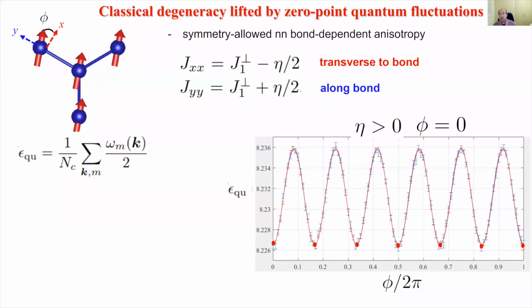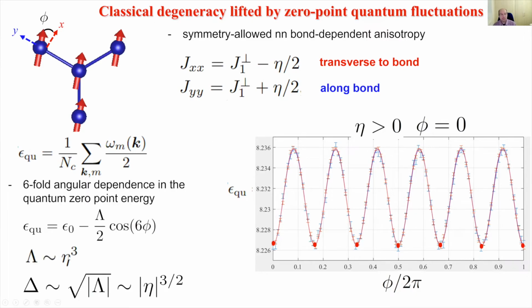And so in the harmonic spin wave approximation, where the energy is (n plus a half) h bar omega, this half h bar omega constitutes the zero-point energy. And if we sum this up for all points in the Brillouin zone of all bands, we indeed find this quantum contribution to the energy depends on angle phi. And in fact we have the expected six-fold periodicity. So it's threefold because of the threefold symmetry of the lattice and the fact that spins rotating 180 degrees don't change the energy. So indeed, this could provide a mechanism to select orientation, say for spins to be along or perpendicular to the bonds. And then doing various scaling analysis, we find that the gap indeed varies with this anisotropy to some power.